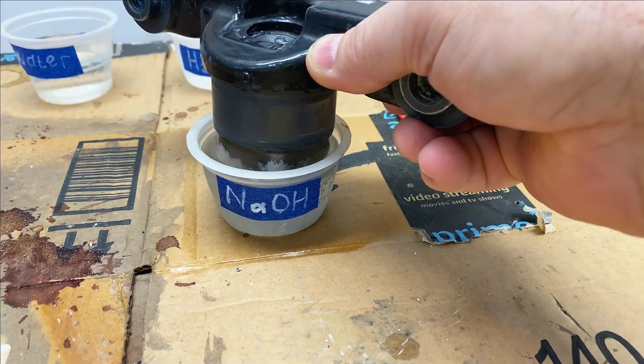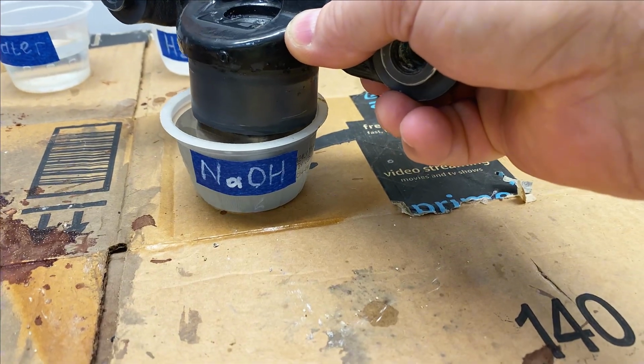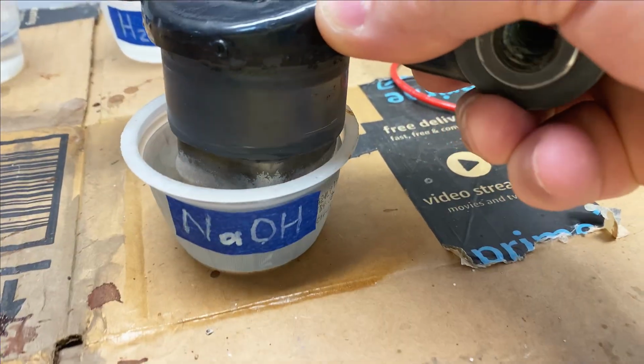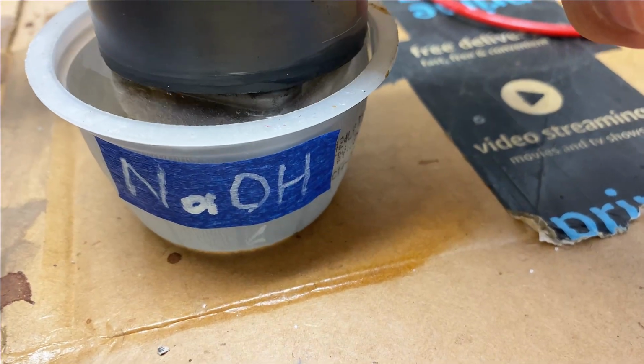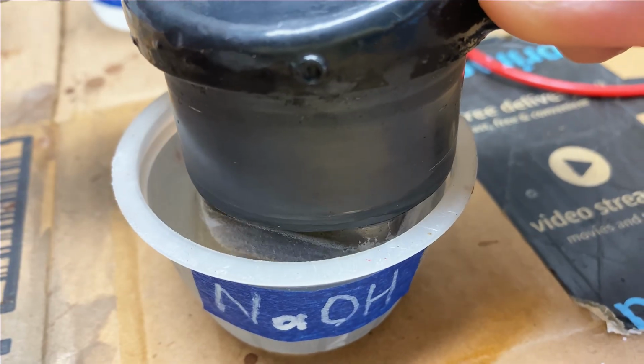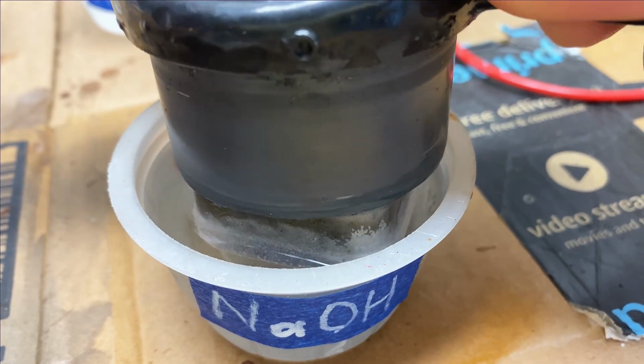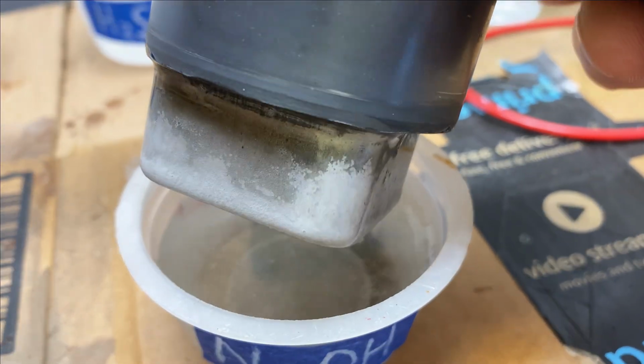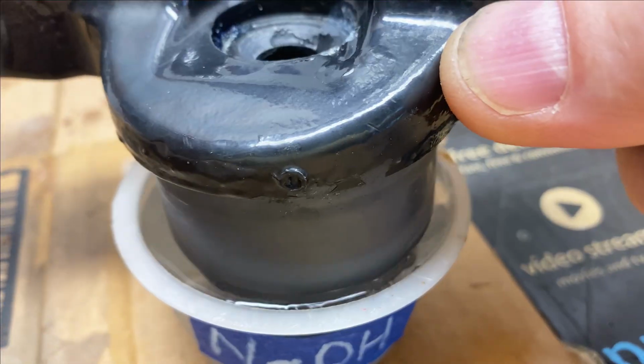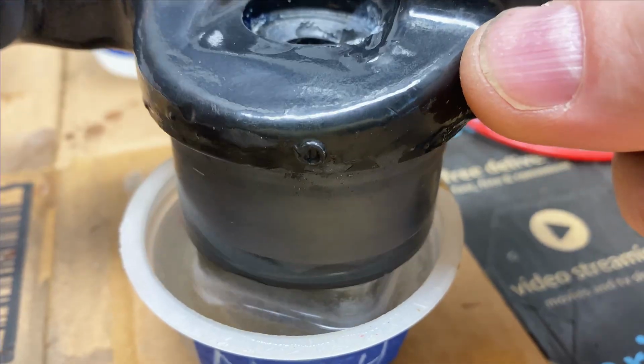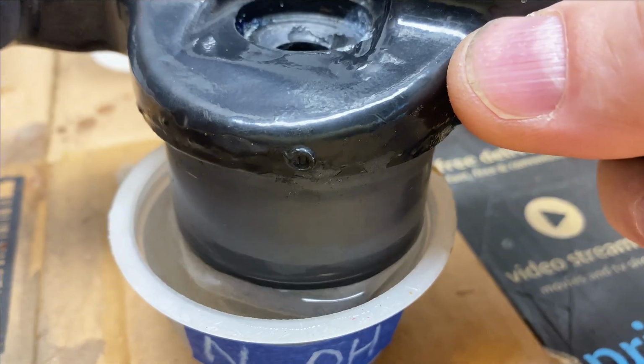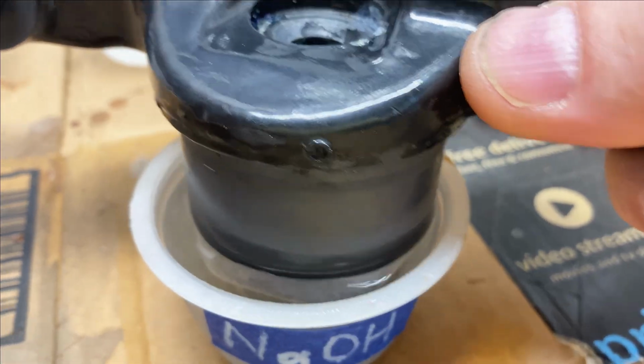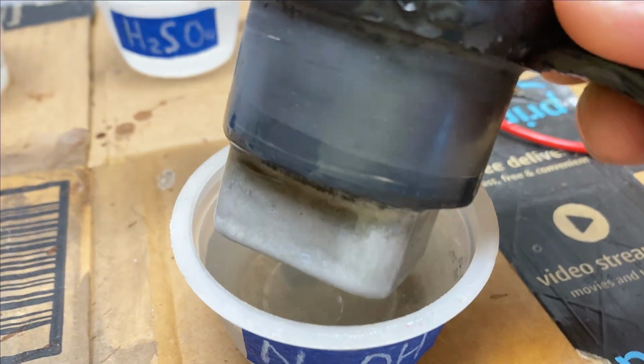I proceeded to degrease the shaft in the alkaline solution, and that was when I got a surprise. A vigorous reaction began on the surface of the shaft. Only aluminum can react to alkaline in this manner. So this is indeed an aluminum alloy, and for aluminum the optimal surface treatment method is anodizing.